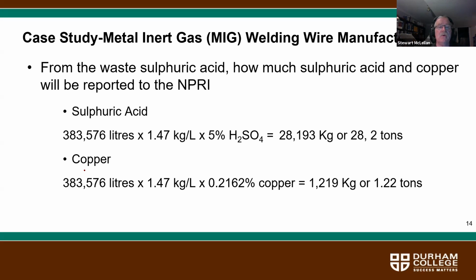So what we do know about the sludge, and this was listed in an earlier slide, is that it contains 5% sulfuric acid on a weight by weight basis and 0.2162% copper. So if you do that calculation, 383,576 liters multiplied by 1.47 kilograms per liter. That was the specific gravity or the density of the sludge, which will change the liters into kilograms. We multiply it by 5% sulfuric acid, and we see that we have 28,193 kilograms or 28.2 tons of sulfuric acid in that waste stream.